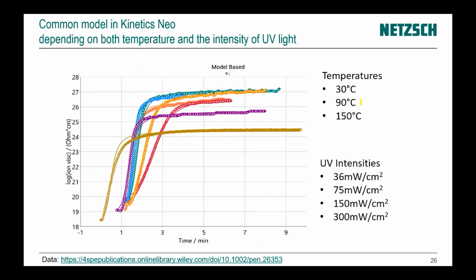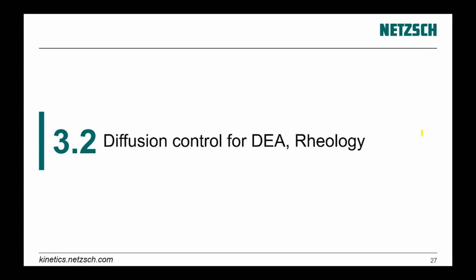Let's go here to the presentation back. Here are our data. The temperature is 30 to 150 degrees C, and UV intensities from 36 to 300 milliwatt per square centimeter. That was the intensities with different UV light, and it could be done also not only for DEA, for DSC as well, and for any different type of measurements which can register your reaction.